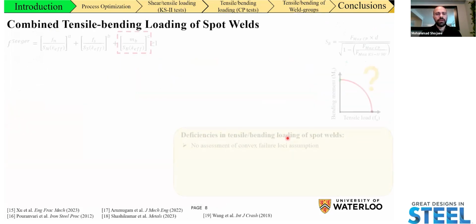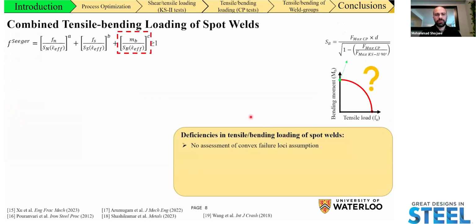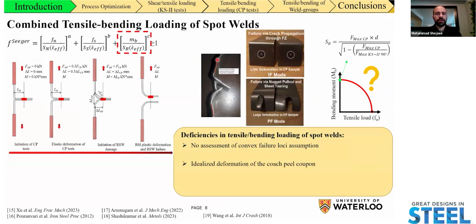Now, the situation for tensile bending loading condition is actually much more complex because we don't really see an effort in the literature in assessment of whether or not the convex assumption of the failure loci suggested by Seeger is accurate. This is really because we have a severe amount of deformation in coach field tests, and it's very difficult to comment on the evolution of the bending moment. As I've shown on the left-hand side here, this schematic really assumes that the upper arm of the coach field coupon remains perpendicular to the lower coupon throughout the test, and that the spot weld maintains its alignment from the beginning of the test to the end of the test.